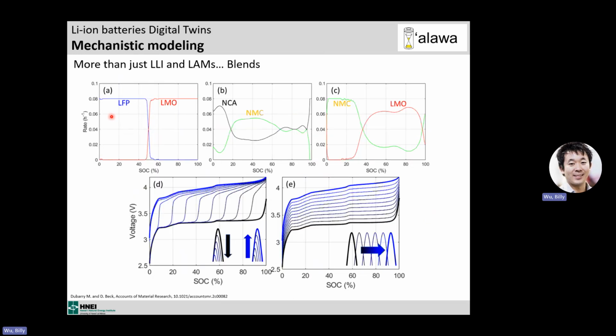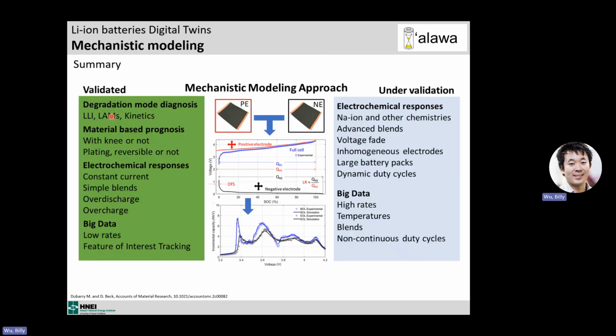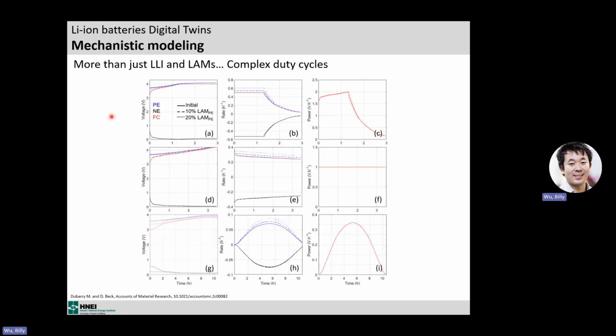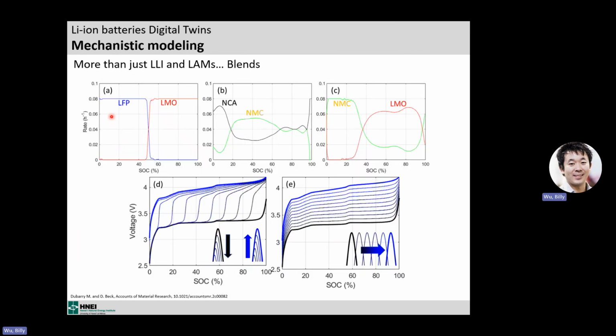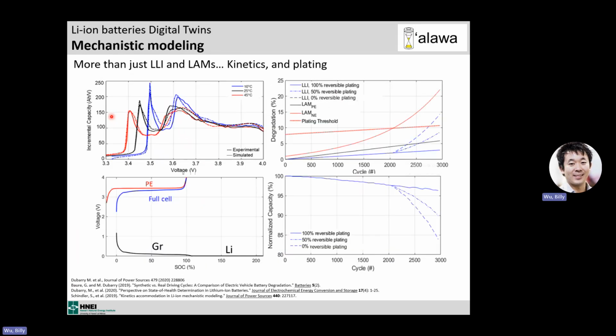And even further, I should have one more slide here, but oops, way too far now. And we prove that actually the variation of the parameters fits an Arrhenius law. So if we have 3 points, we can calculate the Arrhenius slope, and then we can simulate any temperatures from the room temperature data. A really simple step of calibration.